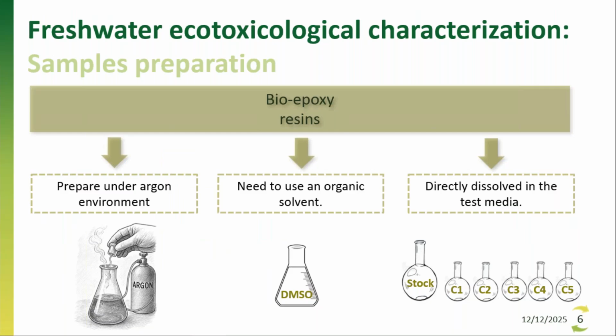So this means that opening of a resin flask must be performed, for instance, under an argon atmosphere to prevent the premature hardening due to oxygen exposure. For instance, we found this the first time when we opened the resins under the environment, and we found out that 2 weeks later the resins have hardened, and in fact they have changed color. So this means that they are changing their properties.